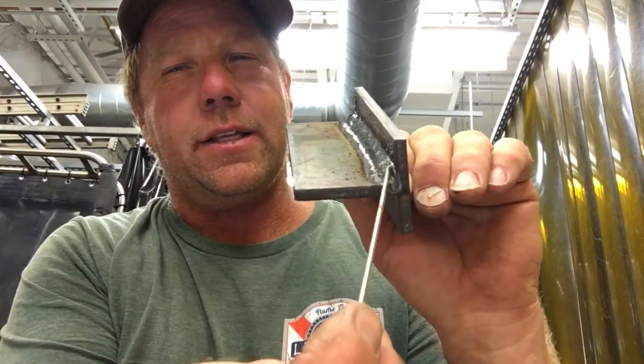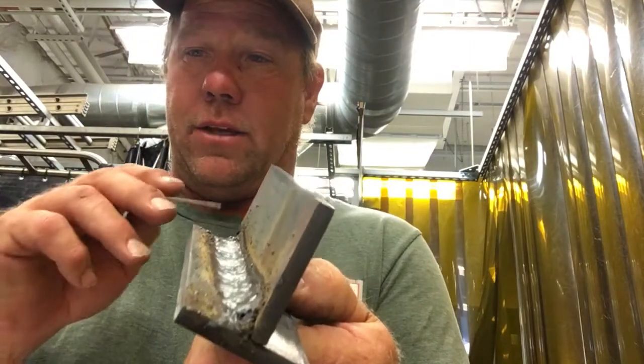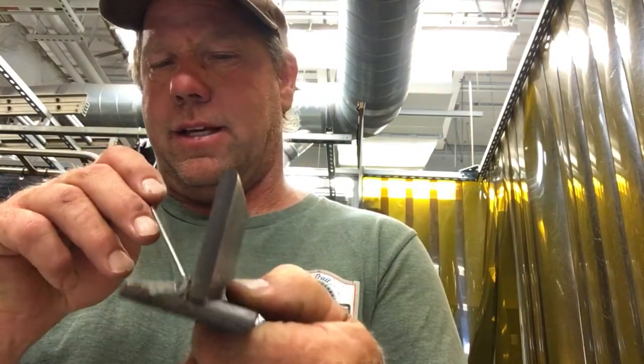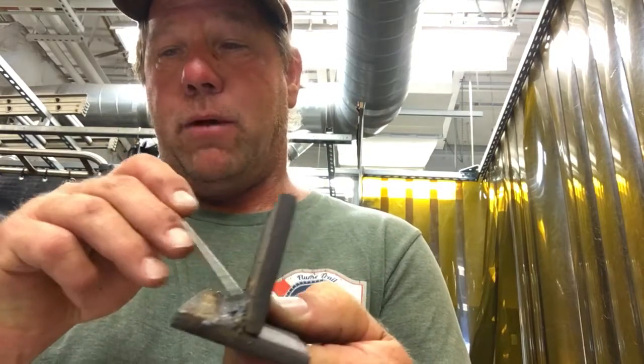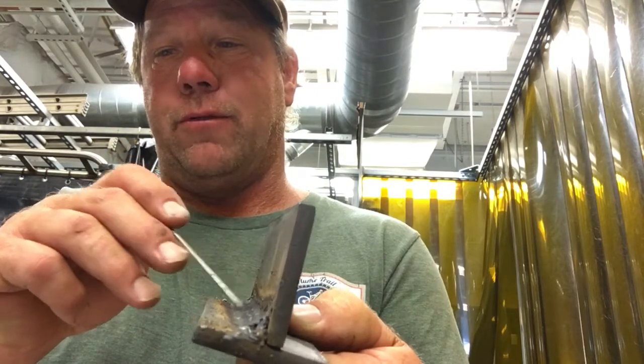So just to give you an idea, this weld was done at 170 amps. I would say 18 volts. I didn't catch the data, but I would guess about 18 volts. 7024 electrode, so quite strong. Decent size, mildly asymmetrical, not bad. See, it walks out a little more on the flats here, maybe a little worse than I thought looking at that camera shot. Walks out on the flats a little more than up on the top. Be good for a 3/16 inch weld. This thing is probably just a little heat layover.